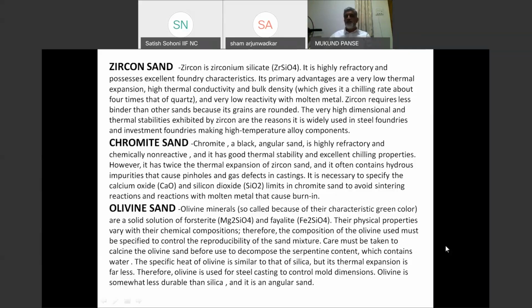The next sand is olivine sand. This is also a mined sand. It is green in color, so called olivine. It's magnesium and iron silicate. The physical, mechanical and chemical characteristics slightly vary depending on the proportions of this. Unfortunately, it is difficult to get exact proportions and exact distribution of sand. It is used mainly for making manganese steel casting, because manganese doesn't react with this Mg and you get a much better surface. However, you have to use it calcined, because there is serpentine in this sand, and serpentine being hygroscopic absorbs moisture and you can get blowholes in the casting.